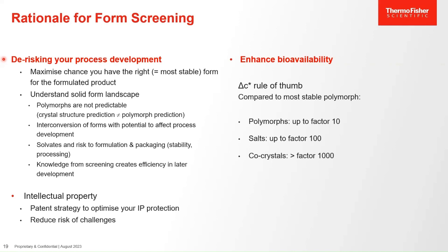Understanding the solid form landscape has other benefits. For example, interconversion of forms with potential to affect process development. It is not uncommon that a different form than the desired form is generated first during a crystallization process. So you generate a metastable form. This then transforms to the more stable form, the one you're looking for. And being able to control that, understand that is important. And you'll get a first indication of relationships between forms from a good solid form screen.